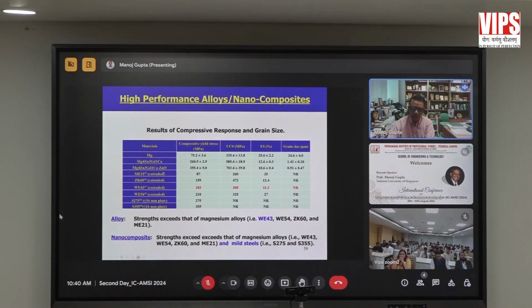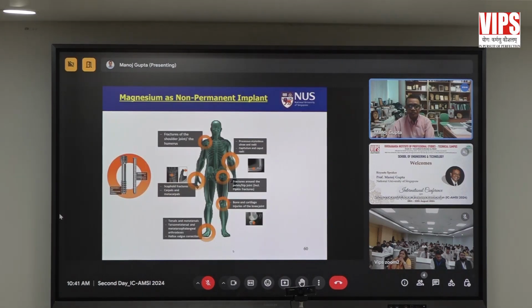Then we put about 2% of zinc oxide reinforcement in there, and I increase my strength by another 100 megapascal in the yield stress, another 100 megapascal in UCS, and my fracture strain stays beyond 10%. That means I still have very good formability. It's not brittle. So the importance of these numbers is that now these exceed that of mild steel or construction steel like S275 and S355. 75% weight saving here, and a tremendous amount of cost saving if you just want to use the alloy. So these are just one of the examples of development of magnesium alloys using the nanocomposite technology.